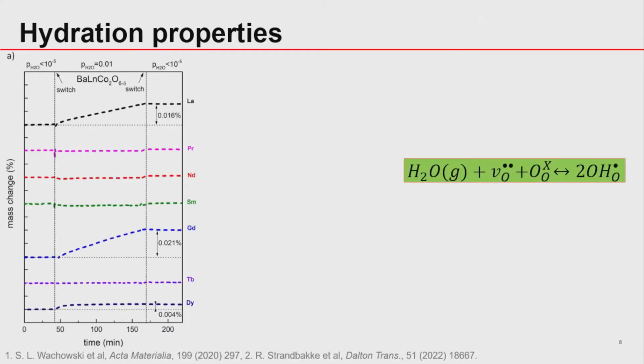Next is to see, if we have different types of lanthanides, what we're going to see. This is a case of a double perovskite sample where in the lanthanide position we have dysprosium, terbium, gadolinium, samarium, neodymium, praseodymium, and lanthanum. The main thing to see is that the gadolinium and lanthanum samples showed weight gain when we switched from dry to wet condition: about 0.021% weight gain for the gadolinium sample and around 0.016% weight gain for the lanthanum sample. But the interesting thing is that when we switch back to dry condition, the weight does not come back. This means the increase in weight is irreversible.